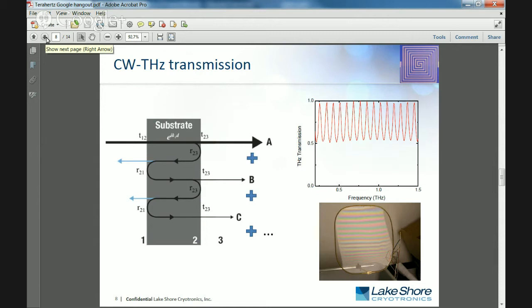So on the right side of that slide, what you see is this interference pattern where we get frequencies with large transmission, and then there are troughs in that transmission. And that's fixed by the thickness of the sample as well as the index of the material. By modeling these multiple reflections in the sample, we're able to extract information about the index of refraction, the complex index of refraction of materials.